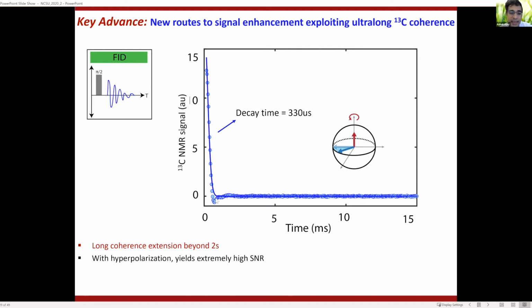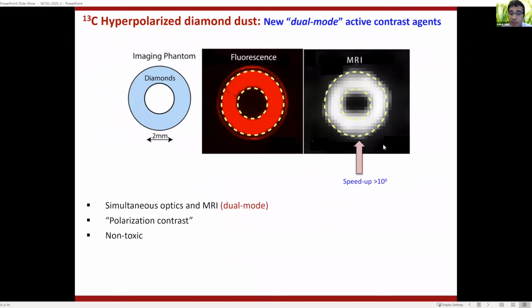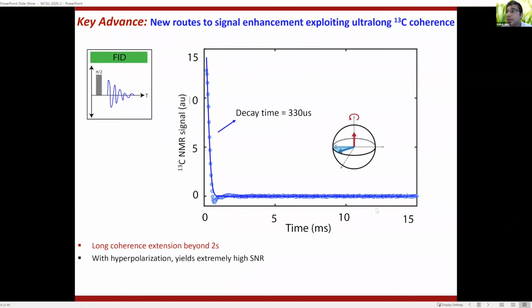And these spins decay very fast, usually in less than a millisecond, because they're all coupled to each other. And this is what you do a Fourier transform of to get the spectrum. And this is the NMR spectrum. So we started investigating whether there's a chance by which we can improve the readout. And as you can imagine, this is very useful even in MRI. So all of these pictures that you got here were all taken with a single pi-half acquire effectively. This is a typical signal that you get.